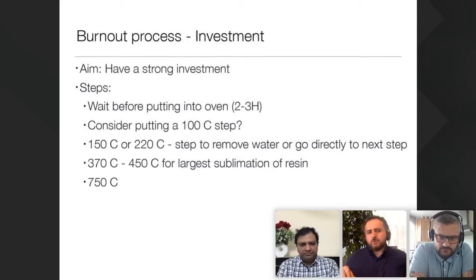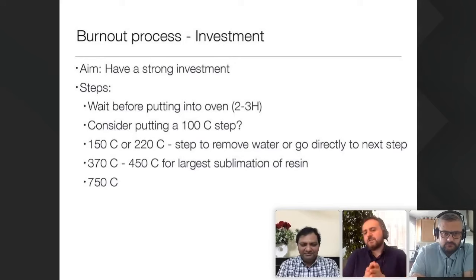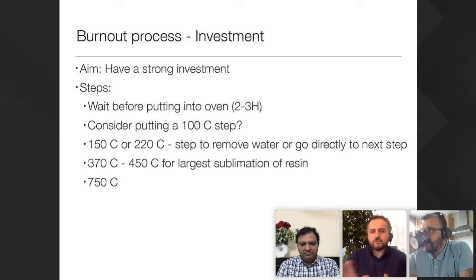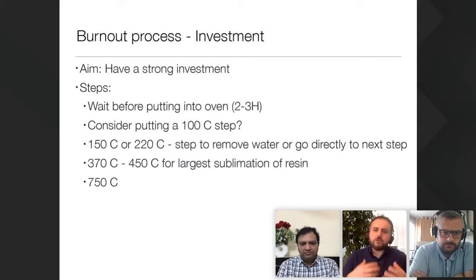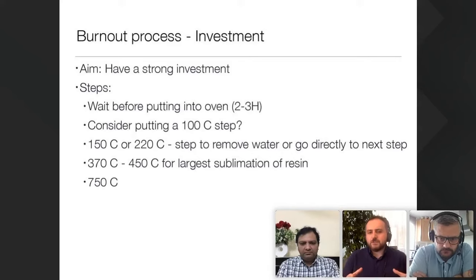Okay, so we want to have a strong investment. How do we do that? First, you mix your investment and leave it, in my opinion, at least 2 hours, but minimum 90 minutes, ideally between 2 to 3 hours on the ground. You don't put it in the oven because it needs to lose its humidity for all the expansion to happen, and you wait - you wait 3 hours. Then there is a very interesting paper where they tested different burnouts, and one of them had a step at 100 degrees.